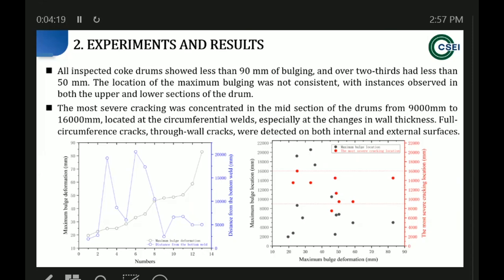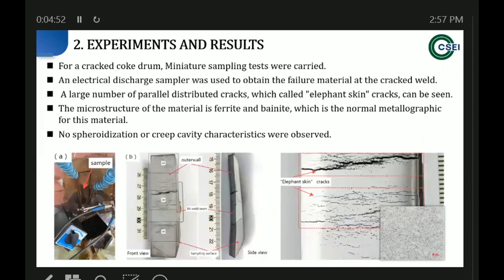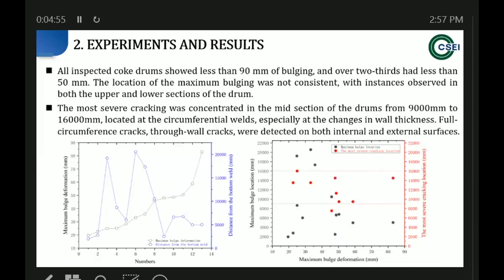And we also studied the most severe cracking, meaning the through wall crack. They are concentrated in the middle section of the drums, from 9,000 millimeters to 16,000 millimeters, the distance from the bottom weld. So I think the location of the maximum bulging is different from the most serious cracking location. And we also see cracks on both the internal and external surface.